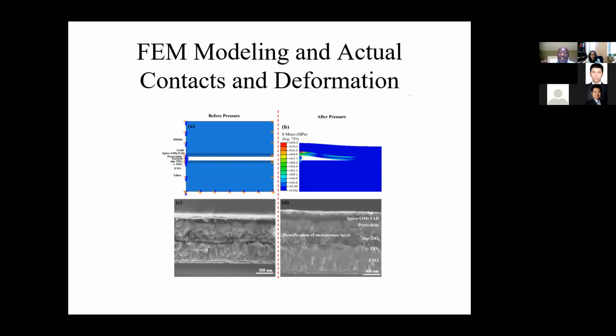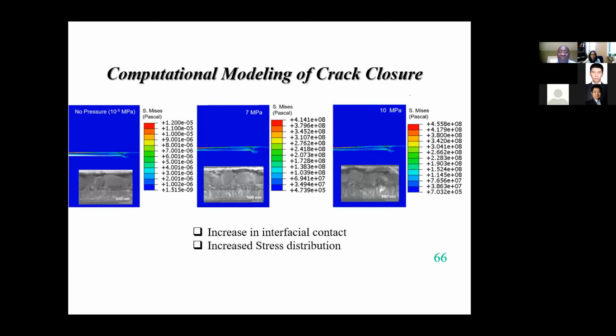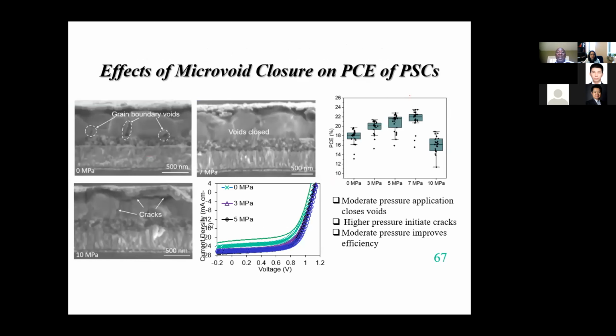And so one can model these contacts and pressure effects. And at the end of the day, you can show that you start closing cracks in ways that enable interfacial contact. And as you enable more interfacial contact, you have more charge transport, which basically improves the characteristics of the solar cells. And so this is why, as we've increased the pressures up to 7 MPa, your efficiencies have increased. But above 7 MPa, you start inducing cracks, which also degrade the power conversion efficiencies of these systems. So by blending mechanics and materials with solar cell development, we're able to actually create structures with world-leading properties.